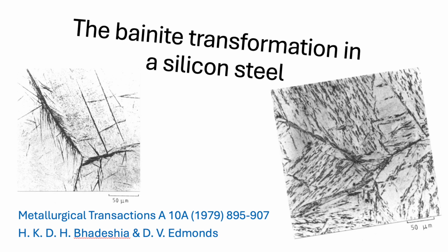When they look very closely at the interfaces where the lower bainite plates were actively growing into the austenite, they observed distinct spikes at the advancing tips. These weren't smooth, curved interfaces. They were sharp, pointy features, almost like little javelins pushing forward. Spikes, not like the feathery UB, but sharp points. Sharp points. And crucially, these spikes had a relatively constant width.